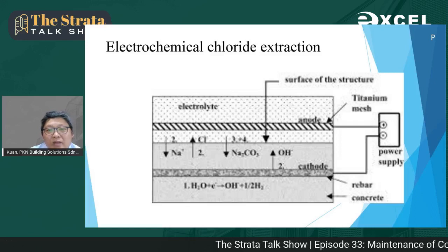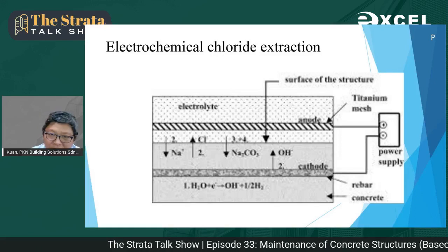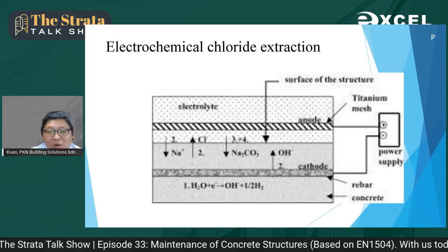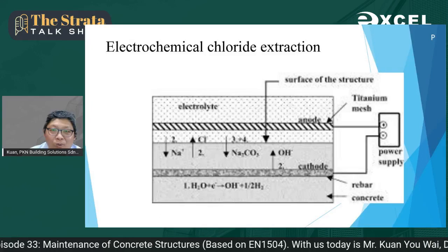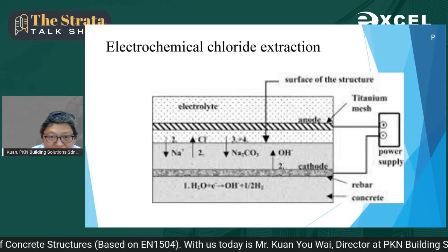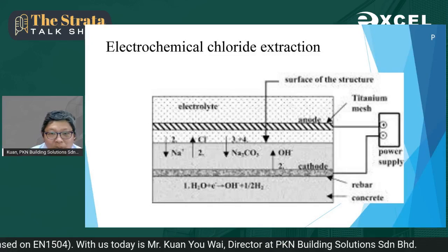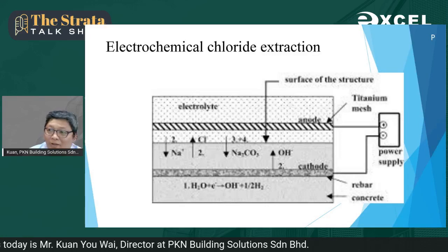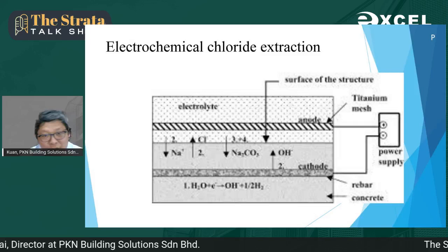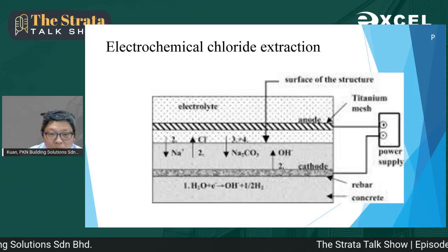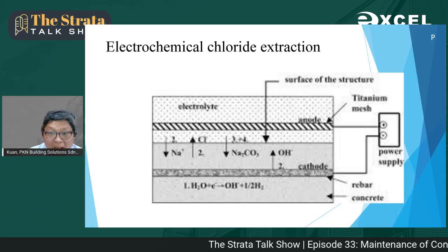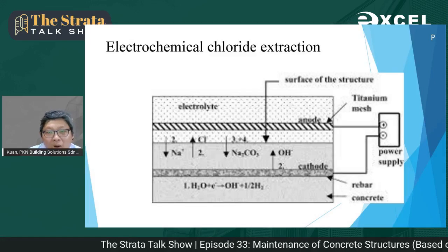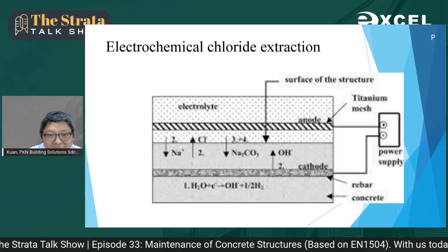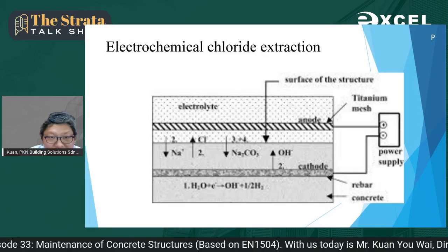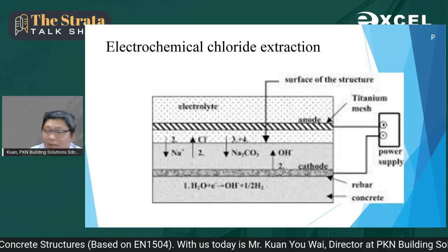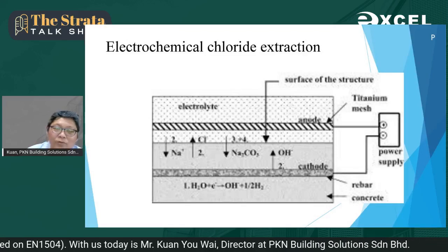And of course, by controlling the voltage, we actually can cause the chloride, which is negatively charged, to move away from the reinforcement steel bar. If we charge the reinforcement steel bar to a negative charge as well, because negative charge and negative charge will push each other away. If the voltage is energized to a higher level, higher voltage, even the chloride gas can evaporate to the air, to the atmosphere. But there is a regulation to it, but I would like to share with you.